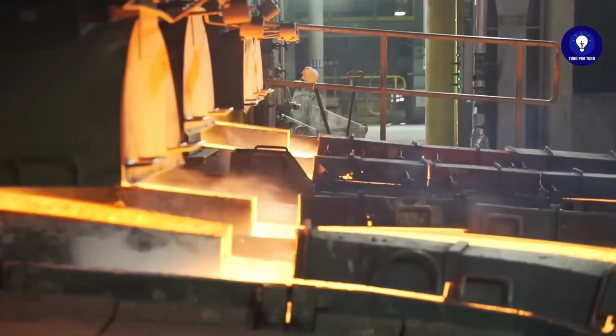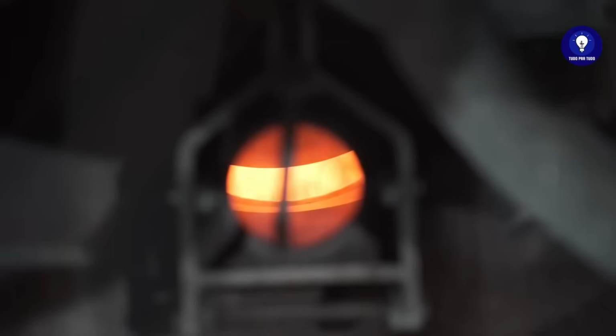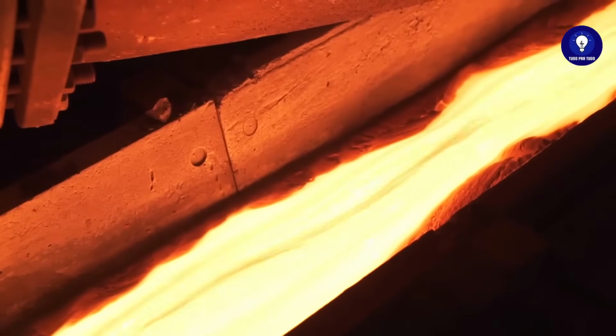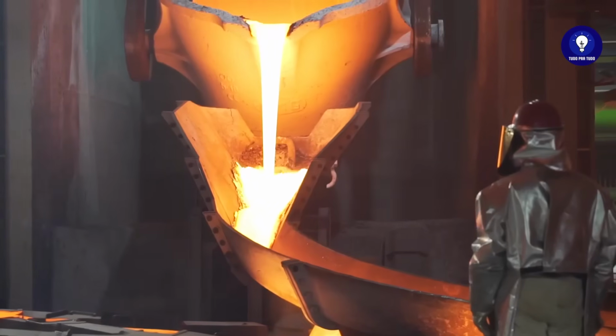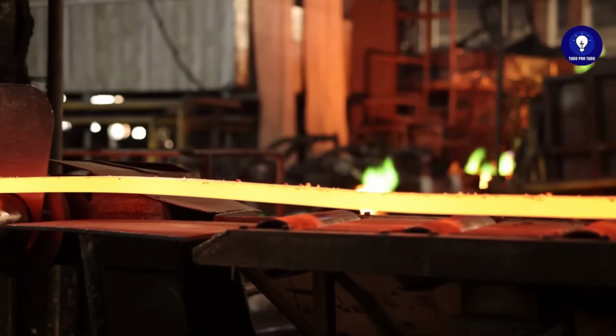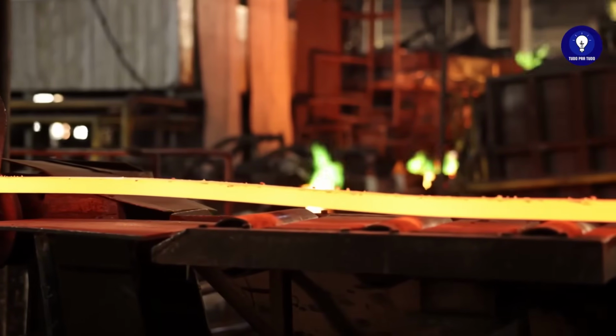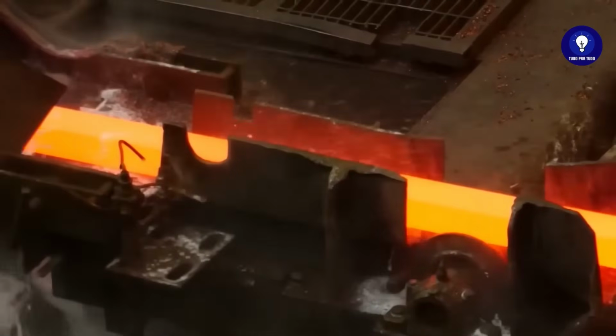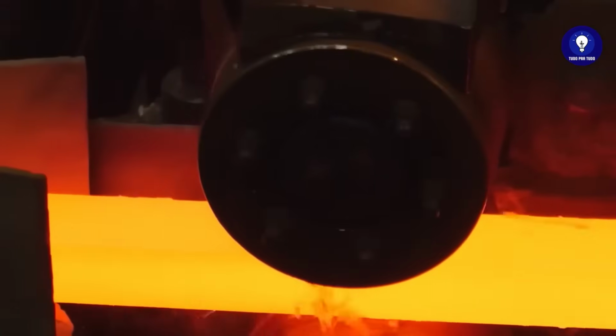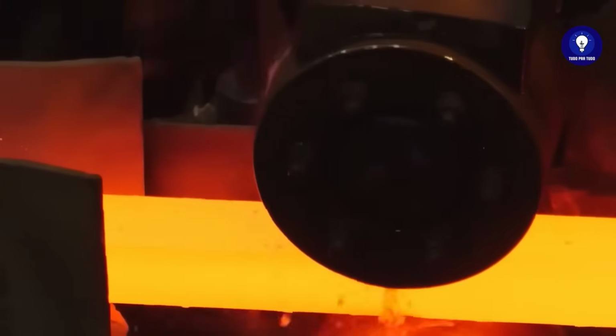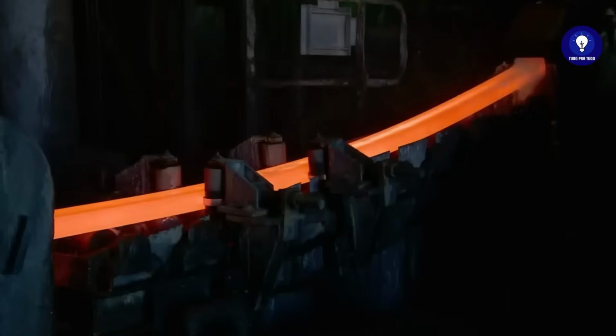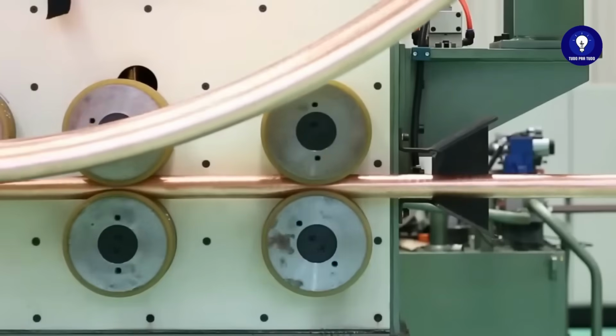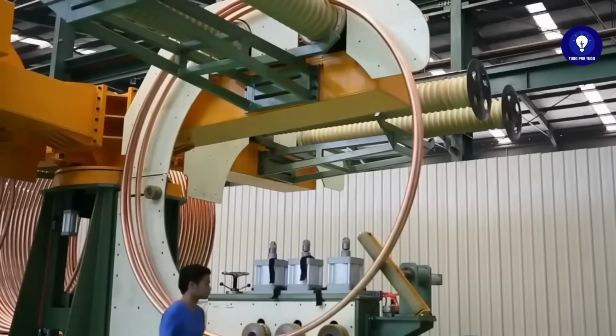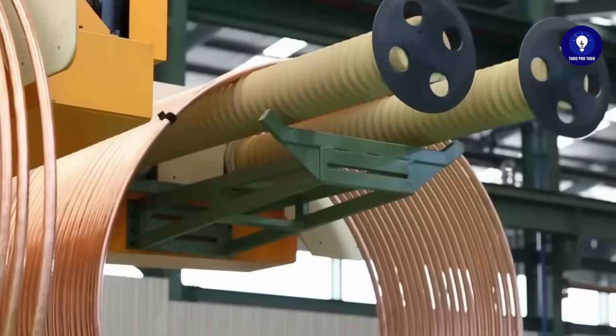This molten copper is introduced into a vertical furnace. The copper melts and flows to the bottom. From there, it is channeled into a mold that forms rectangular blocks about 6 meters long. The molten copper passes through an opening in the mold and is cooled with water, forming a continuous rectangular bar. Rollers significantly reduce its diameter. As it passes through these grooves, the bar is transformed into a copper rod approximately 7 millimeters thick.